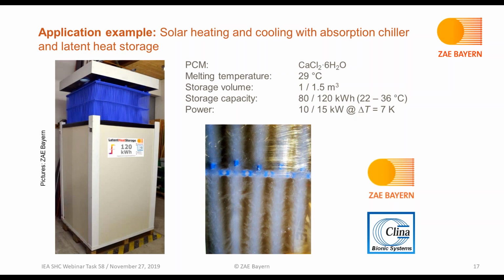So what is the special feature of this type of storage is we're using a so-called capillary tube heat exchanger, which is immersed in the liquid PCM. So the blue capillary tubes are made from plastic to account for the corrosive properties of the salt hydrate. And the picture in the middle shows the PCM crystallizing on the surface of these capillary tubes.